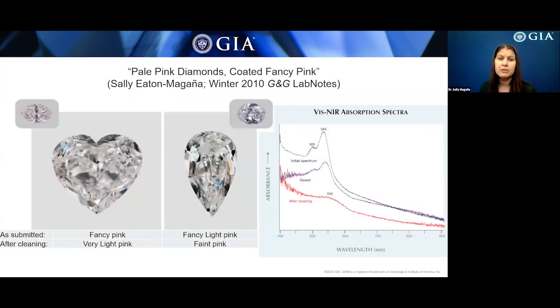Next, we'll talk about two pink diamonds. A pink coating was detected on this 1.5 carat very light pink heart and the 1.68 carat faint pink pear. The diamonds initially appeared equivalent to fancy pink and fancy light pink. Their FTIR and photoluminescence spectra were consistent with type 2A pink diamonds. However, their absorption spectra, as shown on the right, were not.